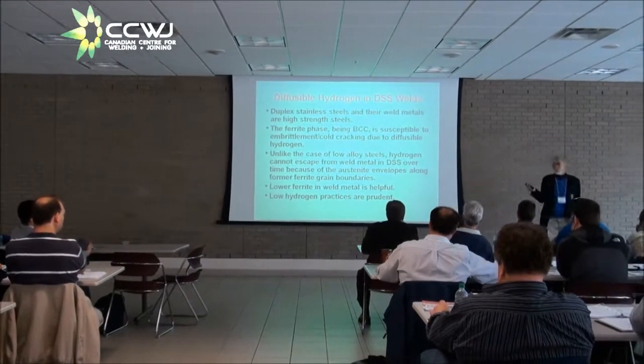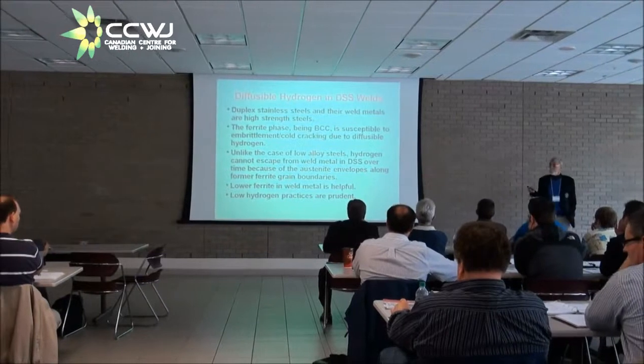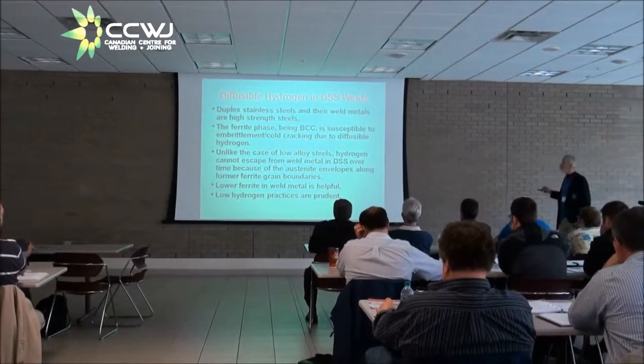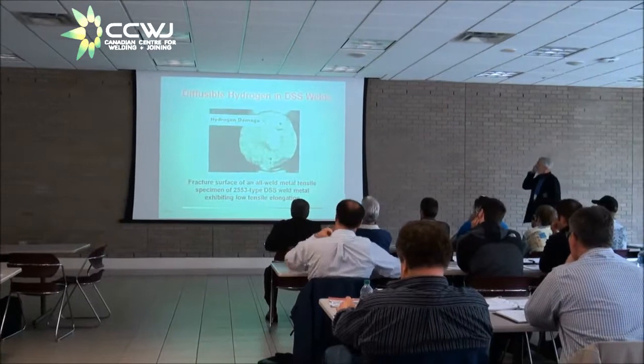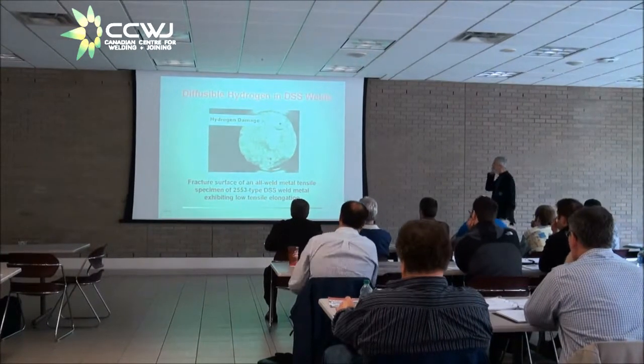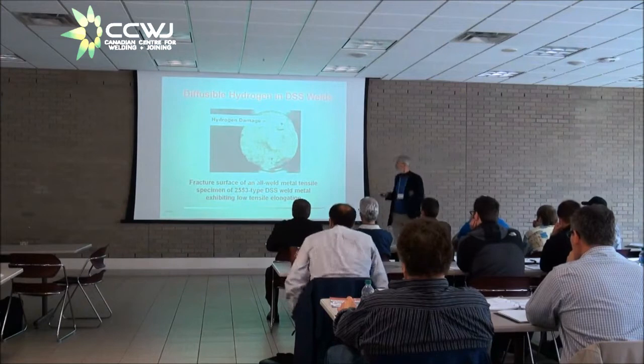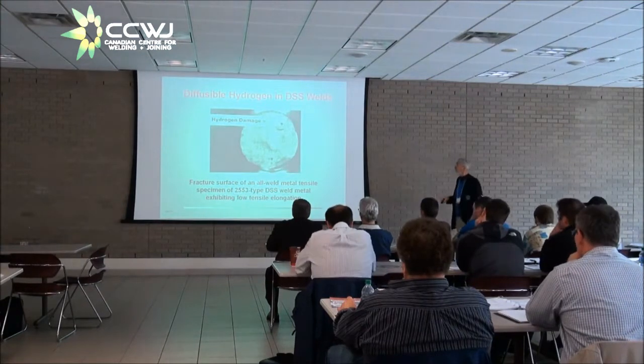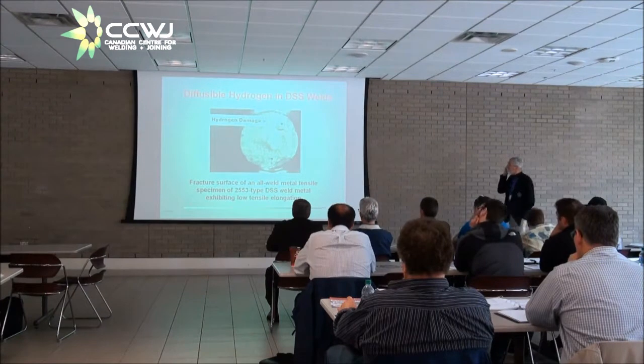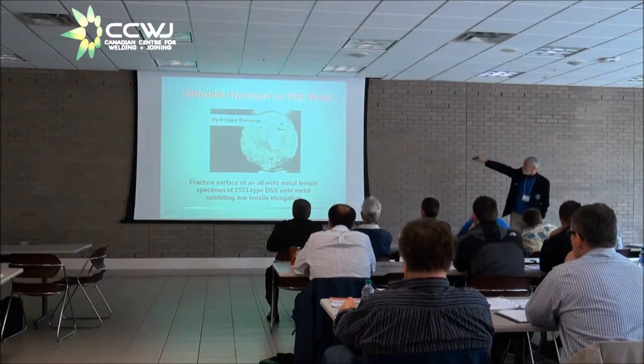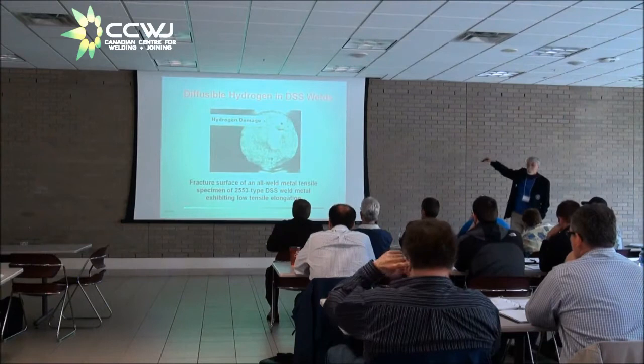They got kind of stuck, and they produced hydrogen cracks. And oddly enough, I managed to do that in the lab with a flux core wire before I realized what was going on. I was looking at a high ferrite weld. So this was a 2553 type weld metal. It had a ferrite number of about 80, if I remember correctly. And what you could see on this is the fracture end of a tensile specimen, a half-inch diameter tensile specimen.